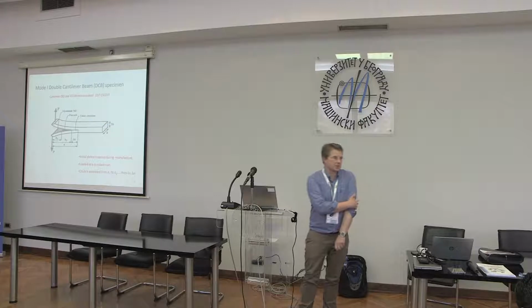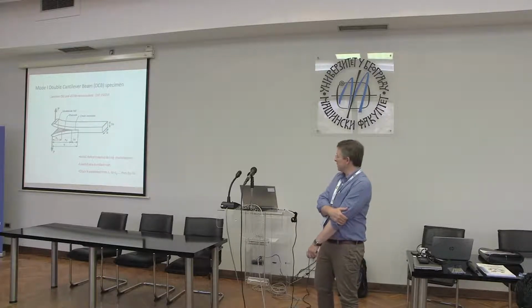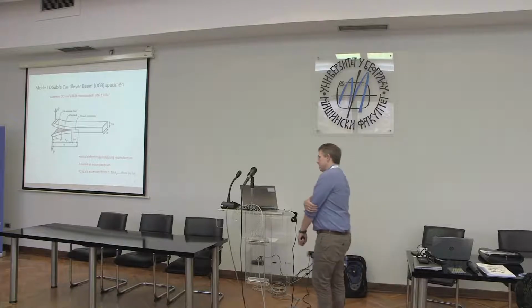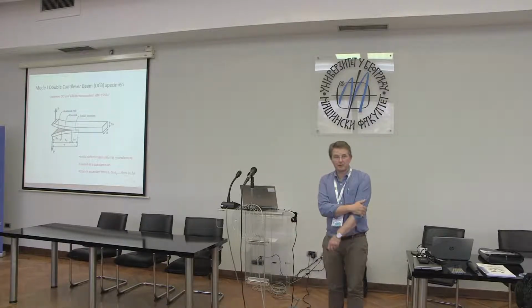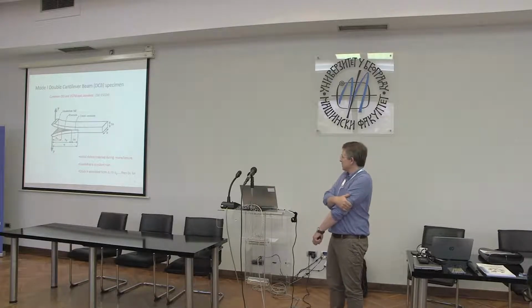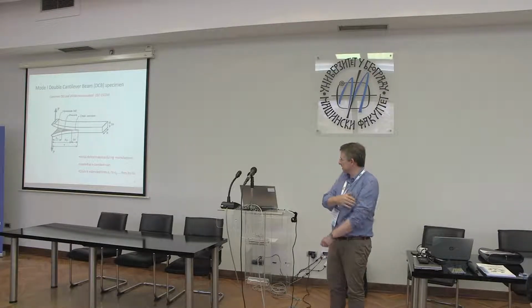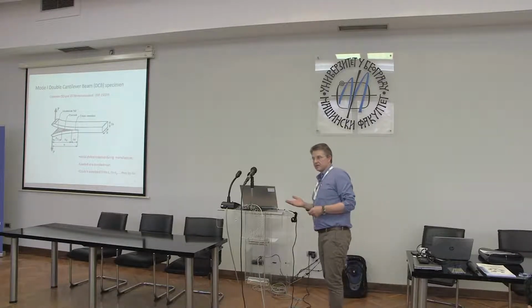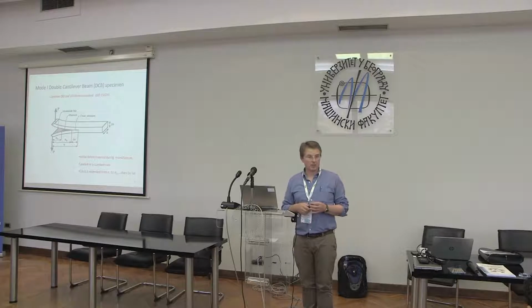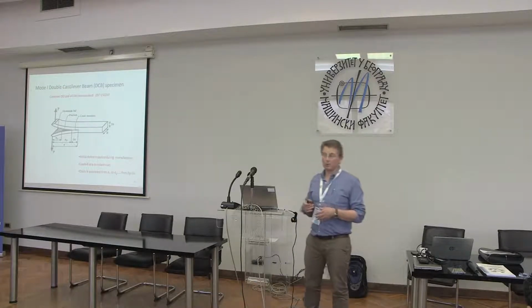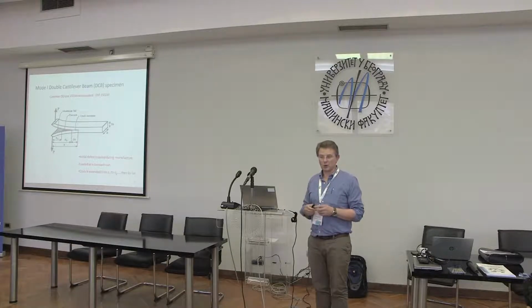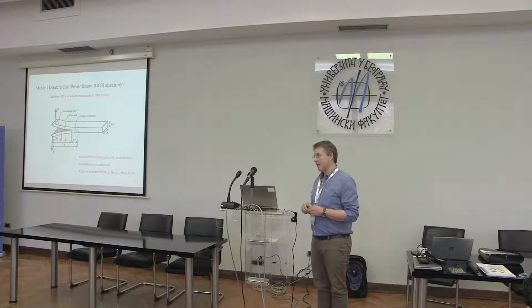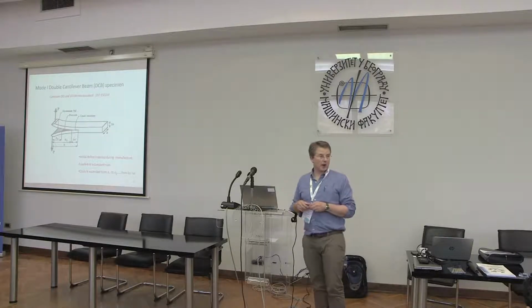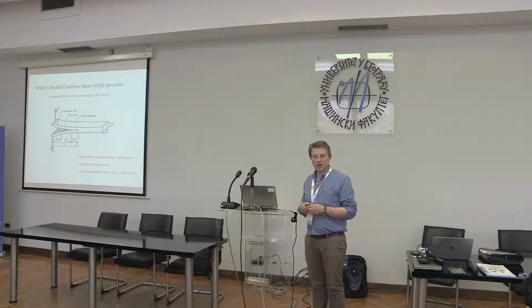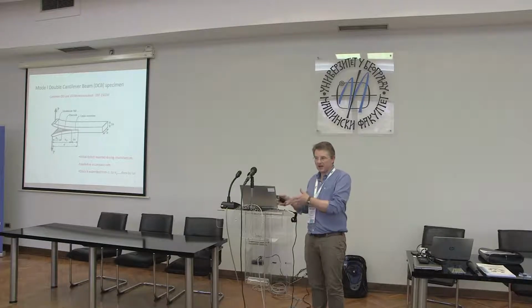So, of course, this type of approach has been enormously useful for people working with composites, and probably the most frequently manufactured composite specimen is called the double cantilever beam specimen. We show it schematically here, where we embed the defect into the material during the manufacture. So unlike a block of polymer or metal where you're going to have a solid block you machined out and then you introduce a crack, what happens with these specimens is we think about the crack during the manufacture, because we don't want to be doing any machining of these relatively brittle materials with carbon fibers, for example, or glass fibers. We want the crack in there to start with.